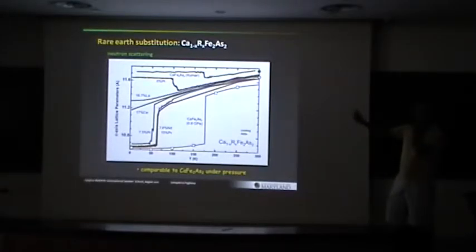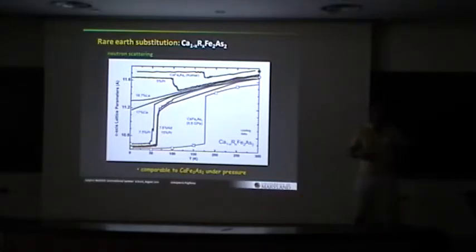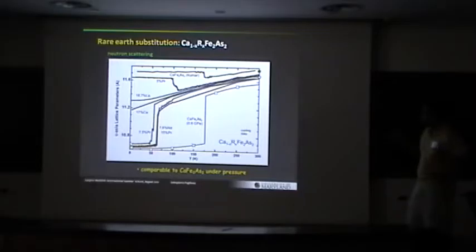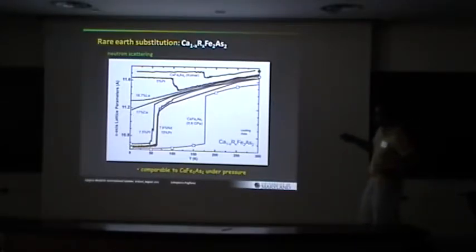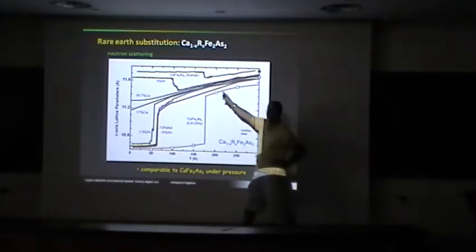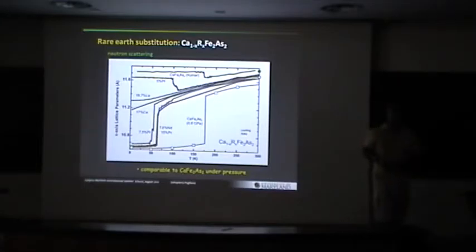Okay, so to summarize, this is the c-axis data for several samples as a function of temperature. This is the undoped calcium compound under pressure, just to compare. So you can see right away that this collapse here is quantitatively more or less the same as these rare earth doped samples under ambient conditions. So here we have a suppression of the c-axis due to thermal expansion, and then a collapse in these. Whereas if we put in lanthanum and even cerium, there's no collapse down to the lowest temperatures. Here's a very lightly doped praseodymium sample, just to show you that when you start with an undoped compound and put a little bit in, you suppress this magnetic transition as well. Sorry, this is a structural transition, but it's coincident with the magnetic transition.